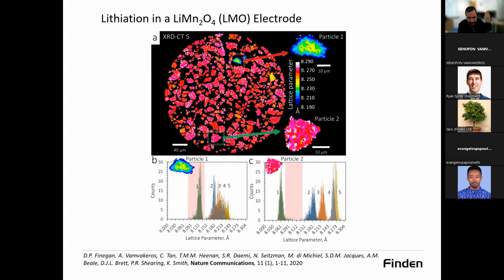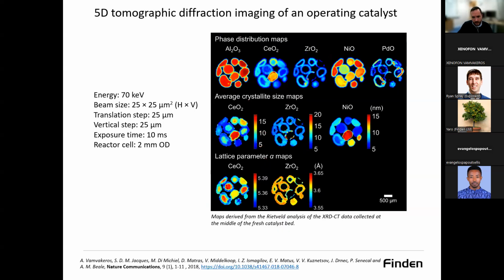Okay, so for example, here particle 1, you can see a particle that is quite an outlier. So the color bar axis corresponds to lattice parameter. This tells us directly how much lithium is captured or released from a specific pixel or voxel in these images from your electrode. And we were able to see that there is quite a bit of heterogeneity in these materials during operation.